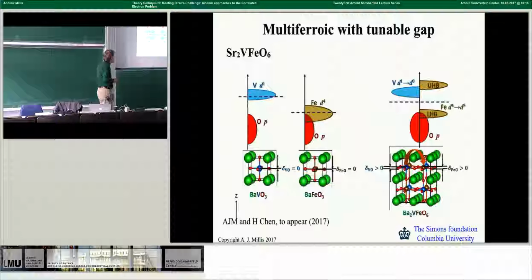Right? You can then go on and try to play, once you have this basic idea, then you can play games in various directions. For example, it is desirable for technological reasons to have a so-called multiferroic, a material which is ferroelectric, so that it's insulating and wants to have an off-center lattice distortion which produces internal electric fields, and is also magnetic. Right? And then you would like to have the magnetism and the electrical polarization talk to each other. Right? So it's very hard to find naturally occurring compounds that do this. Right? But Hanghui observed that you can do this using the same superlattice trick.